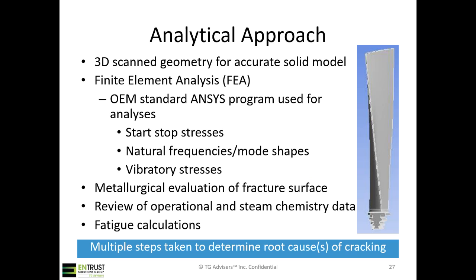So these are freestanding blades for this RCA effort and evaluation. We started out by 3D scanning the geometry for an accurate solid model. So especially in this instance, when we wanted to be able to assess natural frequencies and mode shapes of these blades, having as accurate a model as possible of the airfoil especially is really pretty critical in being able to assess your blade natural frequencies. So the best way to do that, if you don't have the original geometry, since we're not an OEM and we don't make parts, is to 3D scan an actual blade.